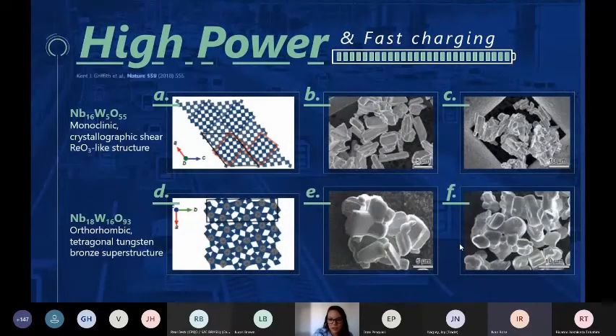Niobium, and we have another class of materials, niobium tungsten oxide materials, that present open tunnel structures that are stable during the cycle and allow the lithium ions to circulate freely in the structure, being able to replace the graphite in the fast charging batteries. In general, this material works because there is a very smart structure with a balance of the expansion of the material during the lithium charging.